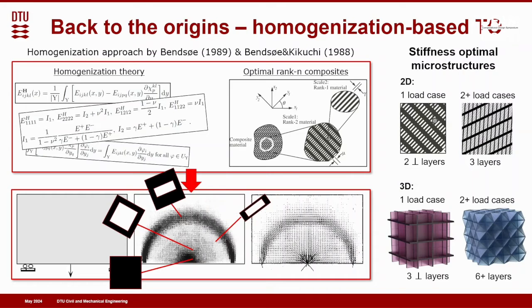Truss lattice structures are not optimal. They are, in fact, 2 to 3 times less stiff than closed wall structures. I'll come back to that later on, but really there has to be good reasons to do truss lattice structures. Usually they are so bad that it would actually be better to do solid structures. For now, I'm going to talk about closed wall structures, and obviously if you're doing a powder-based process, there might be some issues there, but then you have to acknowledge that.